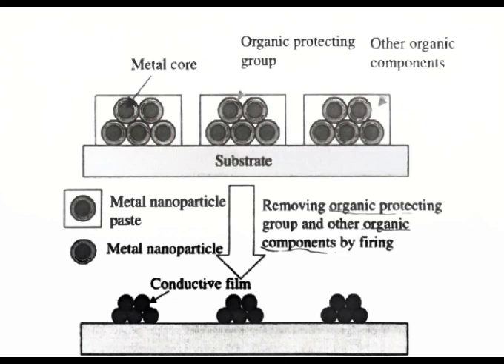So we have these tiny, uniformly sized, coated gold particles all in a paste. How do we go from that to actually creating a circuit pattern? And especially if we're talking about using these on a flexible plastic base, we can't use those really high temperatures. Right, and this is where something really interesting comes in. It's called the quantum size effect. So because these nanoparticles are so incredibly small, their properties actually start to deviate from those of bulk metals.